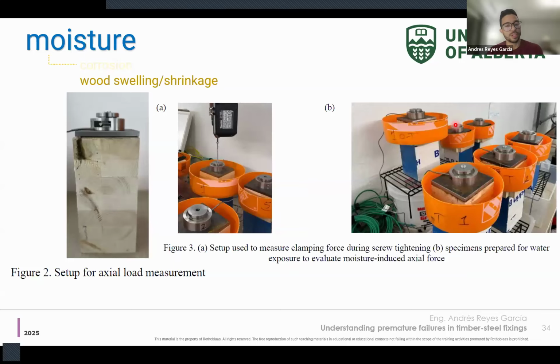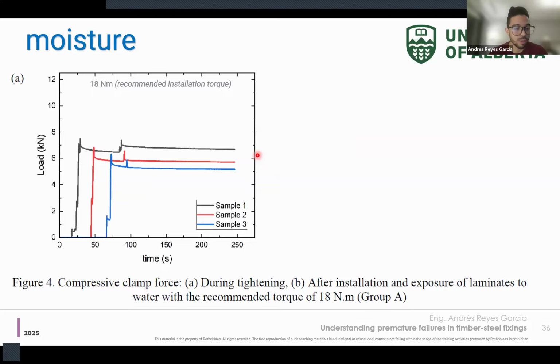We did some tests with the University of Alberta. You see, these are more or less the samples that I showed before. We put them in some cut bucket where we then pour some water, and with load cells, we measure the effect of swelling, the upper force, the force going up. We start with controlled torque, sometimes with over torquing and sometimes without over torquing, and we measure the effect of the swelling. So what you see here, these are the first seconds from installation.